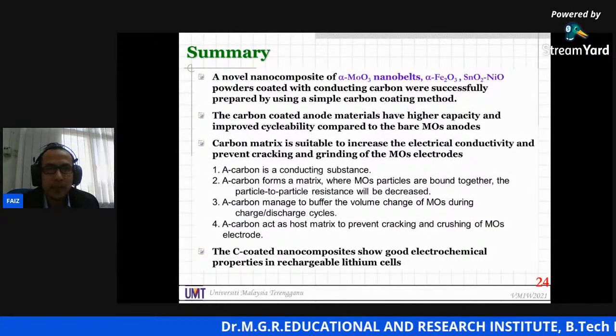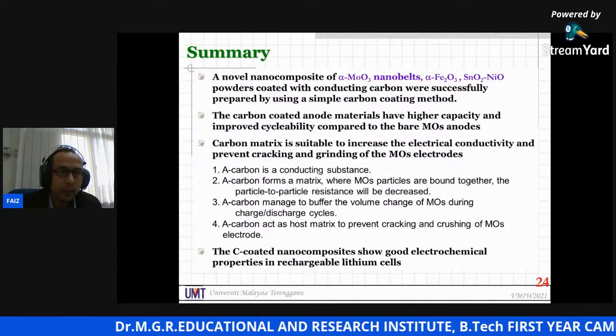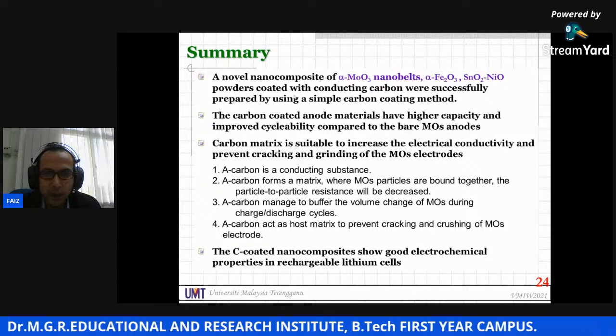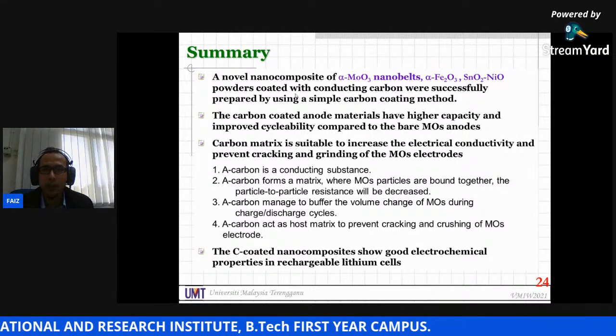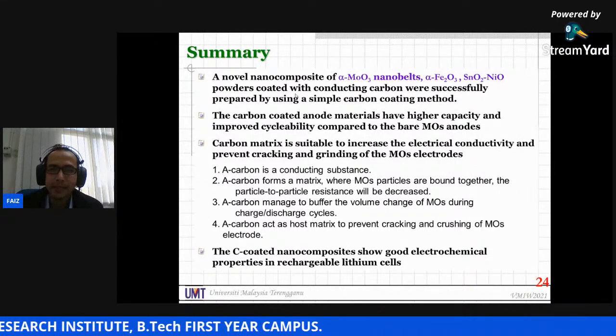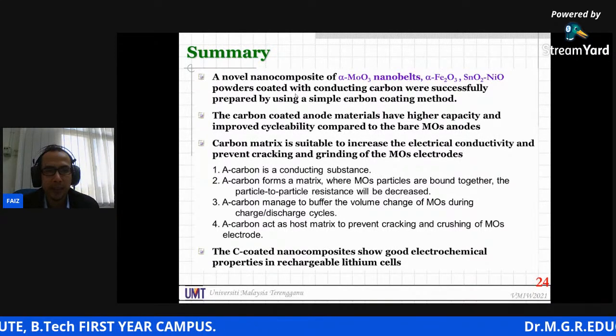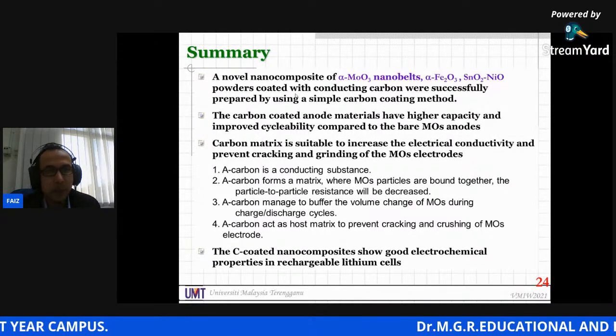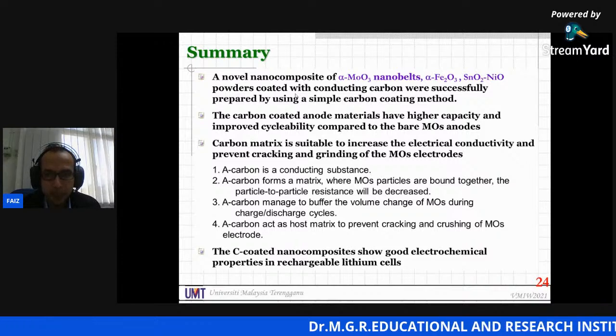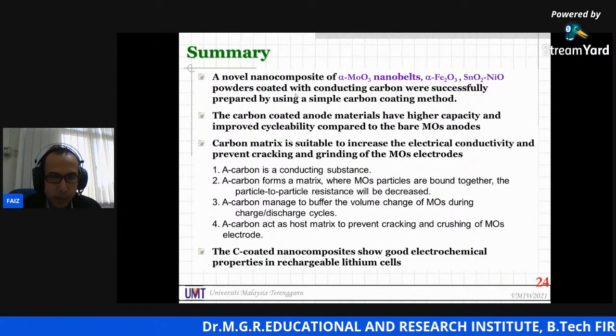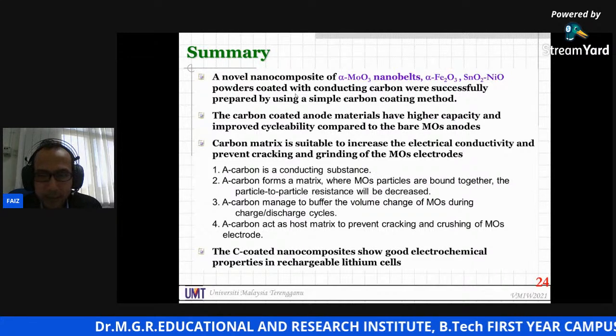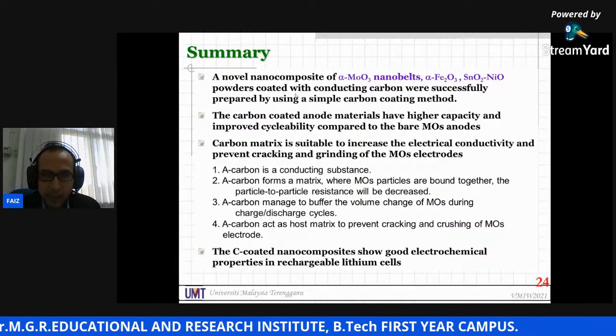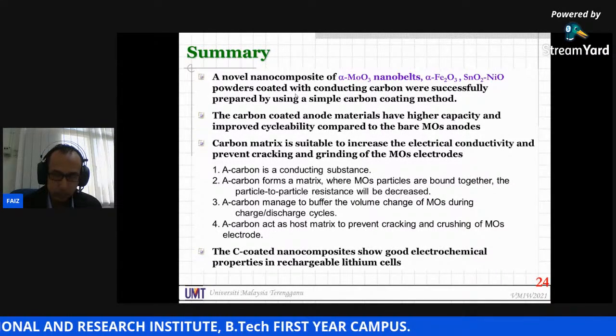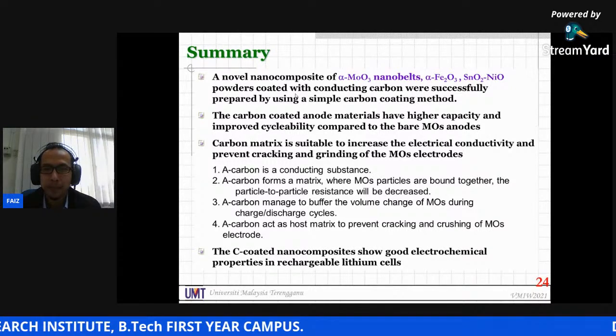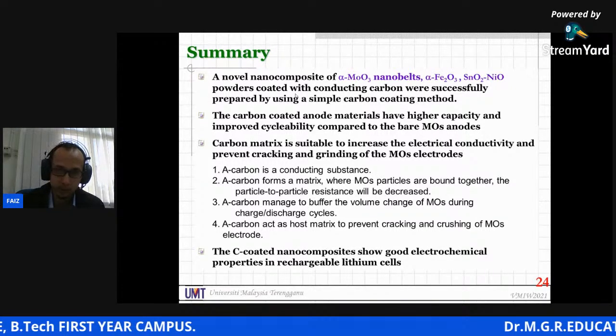All right, as a summary for this part, a novel nanocomposite of molybdenum oxide nanobelt, iron oxide, tin oxide, and nickel oxide powder coated with conducting carbon was successfully prepared by using a simple carbon coating method. The second one, the carbon-coated anode materials have higher capacity and improved cyclability compared to the bare molybdenum oxide anodes.